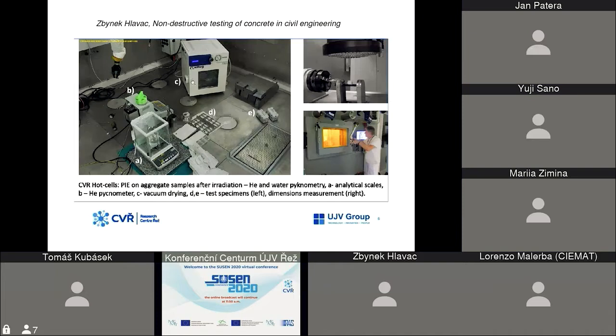What is necessary, especially for the water pycnometry, is some vacuum dryer. It is necessary for some repeatability of the test. Because when we do one check of the density, it is not enough, so we have to dry the sample again, and repeat. It is quite a time-expensive process.